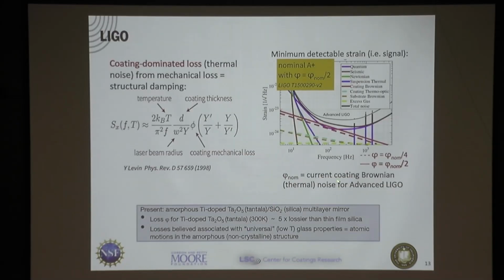Okay, so right now, what they're using is the low index material is silica, which has an index of 1.5. The high index is a sort of random material. It's titania-doped tantala. It's sort of random in the sense that nobody designed that material to be low loss. It was chosen because it is something that people in the optics community use for a high index layer. And so that's what they've been using. The added titanium helps with its index of refraction, and they do a lot of annealing. It has to not crystallize. I didn't even mention scattering. You cannot have any scattering at all. So there can't be any nanocrystallites in there because they would lead to scattering.